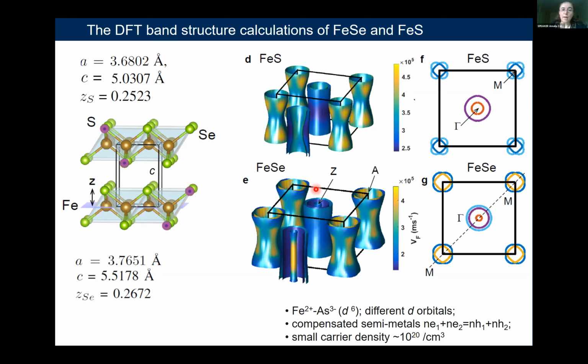These are compensated semimetals. So the hole bands live at the center of the Brillouin zone and are two-dimensional cylinders, and the electron bands live at the corner of the Brillouin zone. Comparing iron selenium and iron sulfur, from the band structure point of view, we can notice that the differences are quite subtle, and the number of holes varies, being only 2 for iron sulfur, but predicted to be 3 for iron selenium. What changes significantly between these two systems is actually the z-axis value, suggesting that we can expect certain warping effects as we move across the series.